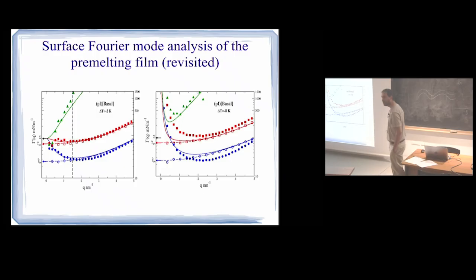Okay? Wait. Yes, go ahead. It's diverging, and I thought this was a sign of the roughness. No, you get all of the surface tensions converging to a value when you are rough, and they diverge when you are smooth. And how do you prescribe in the simulation that you have the prism basal phase? Well, I just prepare the lattice with the right orientation. I just prepare the lattice such that the vacuum that is exposed to the ice slab is in the right orientation.